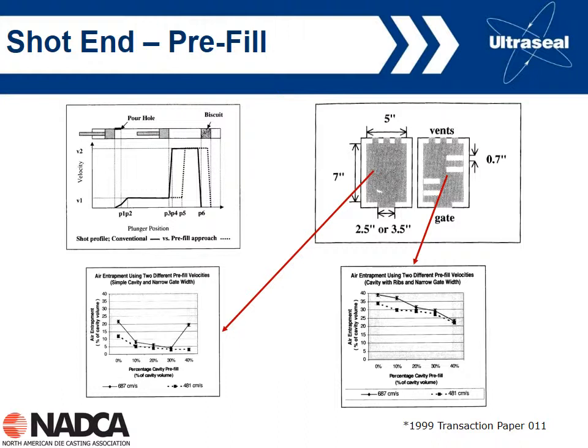And we can see generally we get a decrease in the amount of porosity until we get to 30%. For the lower slow shot velocity, it stays pretty low, but for the high slow shot velocity, we get an increase in gas entrapment if we go to 40% pre-fill. However, if we look at the more complicated die, the data shown here on the bottom right, again, air entrapment versus percentage pre-fill. In this case, the amount of porosity is higher, not surprising because it's a more complex, more turbulent fill. But for all conditions, we get a decrease in the amount of porosity as we increase the amount of pre-fill.